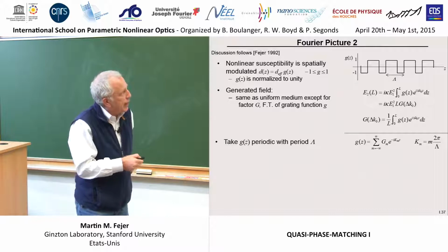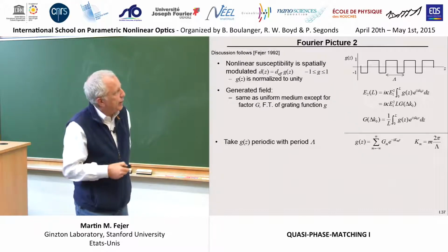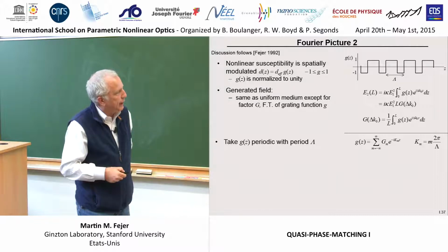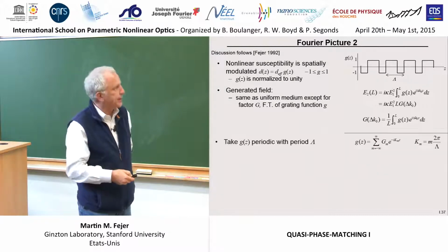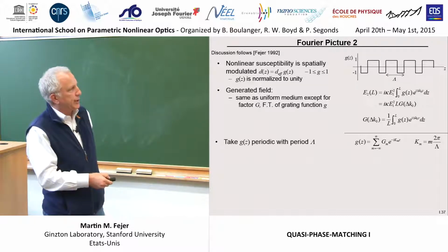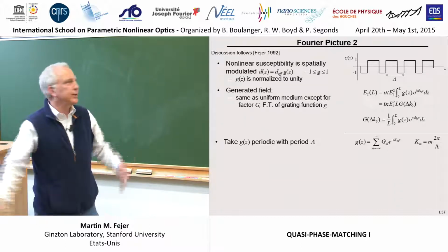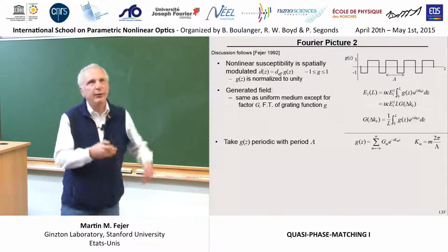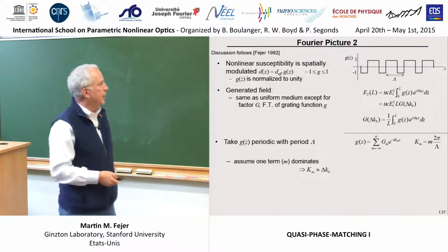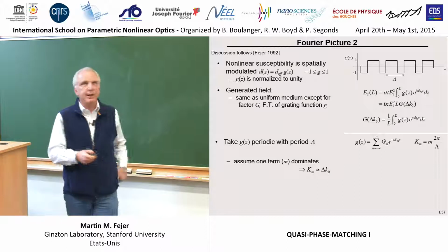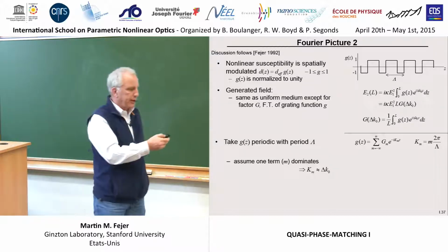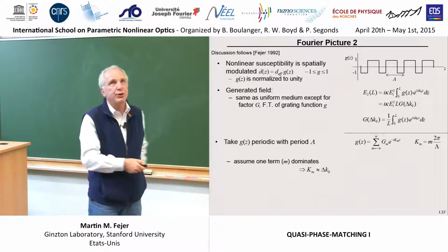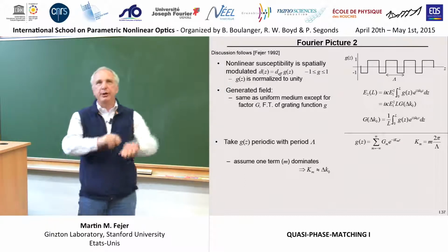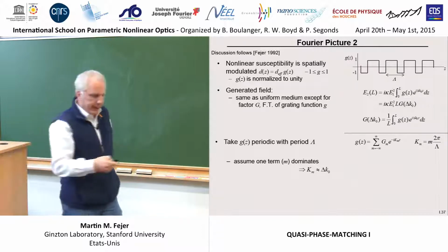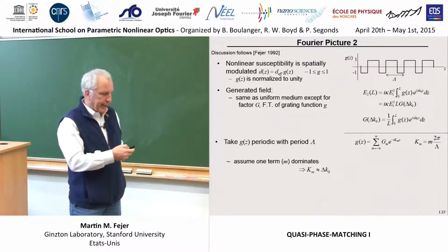If our structure is periodic, as it is in the simplest cases, we can write it as a Fourier series, with spatial harmonics of the fundamental spatial frequency 2 pi over lambda, and each integer overtone of that will have a weight in our Fourier series for that function. So usually you choose this, as we discussed, to put one of these spatial frequency components equal to delta k or close to delta k, and it will then dominate this integral, and usually you can ignore those other Fourier components that aren't close to phase matching.